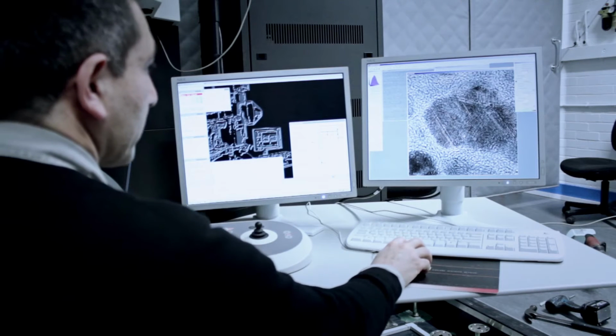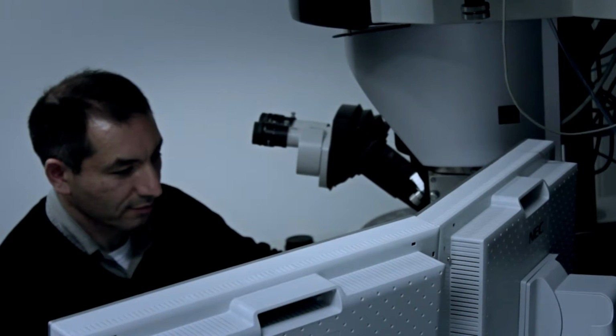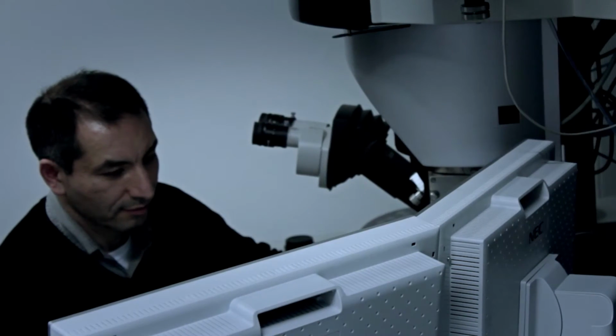And we can study that by slicing it in 3D using focused ion beam microscopy, or we can slice out a very fine region that we may want to study at the atomic scale so that we can study exactly the local chemistry of the crack tip at an atomic level and to understand whether it's corroding because the grain boundaries are denuded of particular elements. That is really where the FEI ChemiSTEM comes in. It's at the end of a long series and following right the way down. But at that point, the FEI ChemiSTEM provides us with that atomic scale, high resolution, along with chemistry, so that we can understand really what lies at the heart of these damage corrosion processes.